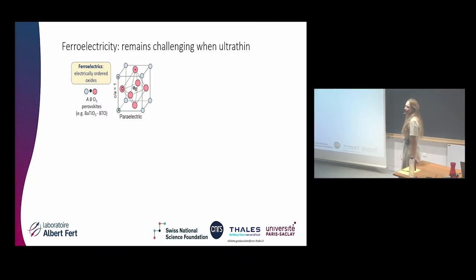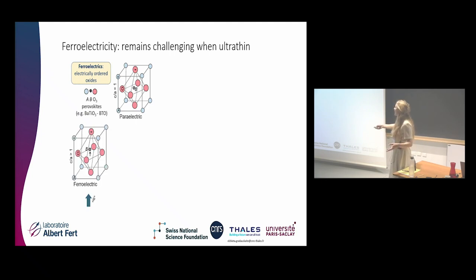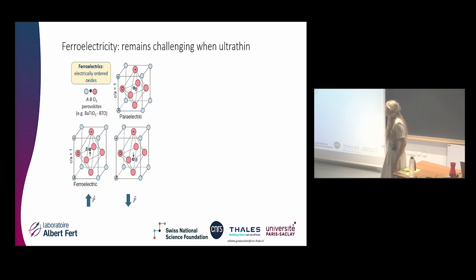I guess this morning there were many talks mentioning ferroelectrics, so I don't have to go through it in such detail. But the idea is that in my work, we will consider perovskites, ABO3 perovskites. If you think about a cubic paraelectric perovskite, you will get polarization if you displace cations with respect to anions. If this middle cation moves upwards with respect to the oxygen cage, you get polarization up, and if it moves downwards, polarization down. So this is our ferroelectric, non-volatile, two remanent states. And the key concept here is that we can use an external electric field to switch between the two. That's the idea behind all the memories written with ferroelectrics.